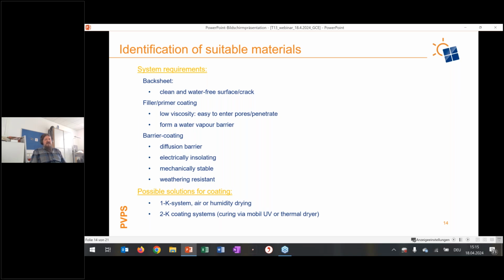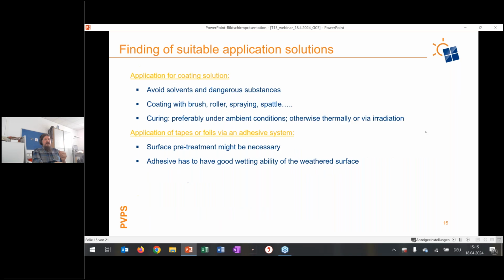also weathering resistance. We looked into different coating systems: one-component coating systems that just cure under air or humidity, or two-component systems that cure via, for example, UV irradiation or some thermal exposure. What we needed to secure with our repair coatings is good material compatibility. So our coating solution needs to have good adhesion to the polyamide surface, and we don't want any migration from the adhesive or from the coating into the backsheet and the other way around.